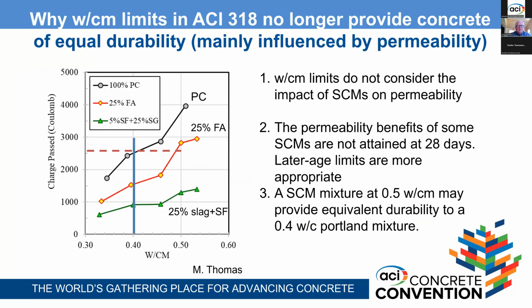And just as an example, this is some work that Michael Thomas did, showing the Coulomb charge on the vertical axis versus water cement ratio on the x-axis. It shows three different concretes: straight Portland cement, 25% fly ash, and 25% slag plus about 5% silica fume. It shows that at the same 0.40, you could have a 2,500 Coulomb concrete with the Portland, about a 1,500 Coulomb concrete with the fly ash, and less than 1,000 with the green mix there at the bottom.